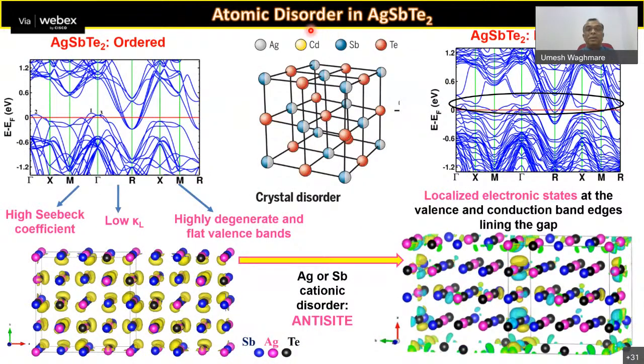So how does this disorder have an effect? This is a perfectly ordered electronic structure of silver antimony telluride, which is almost semiconducting, very metallic, with overlapping bands. But the moment you introduce disorder, you get these states which are in the gap, and those electronic states you will see are localized on the defect site. These clouds essentially indicate electron clouds in the crystal calculated from the standard model, and they are highly localized on those defects. Whereas in an infinite, perfect crystal, they are beautifully extended all across the crystal and carry electrical current.